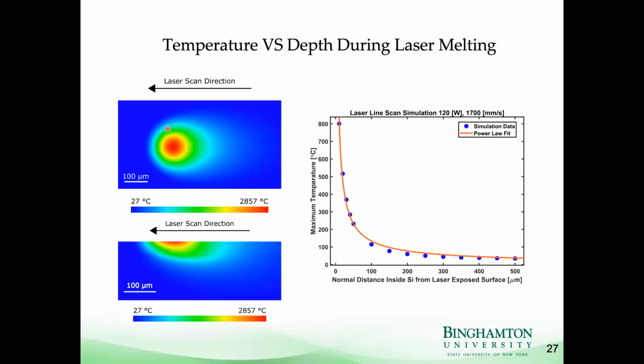We've also done simulations. These are some simulations that we did a while ago. We've since done some more complex simulations that take into account surface tension and various other effects. But this basic model shows that if the thickness of the silicon is typical of a silicon chip, 30 or 50 micrometers, that the temperature rise on the transistor side is not overly large.